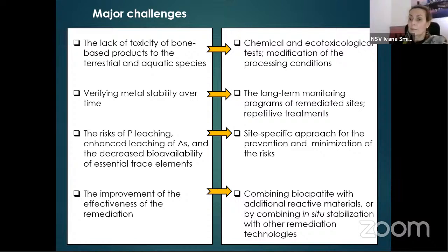This must be done by conducting chemical and ecotoxicological tests using these materials, and if they do not comply with the standards, the process conditions must be modified, the processing conditions of the animal waste. Then the metal stability over long periods of time must be verified, and it is conducted by long-term monitoring programs on the remediated sites. And if a lack of stability of metals is detected, then repetitive treatments must be done.